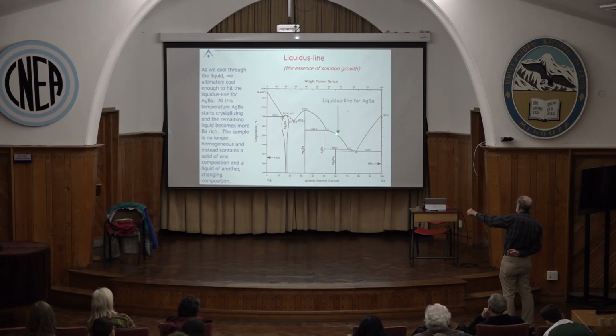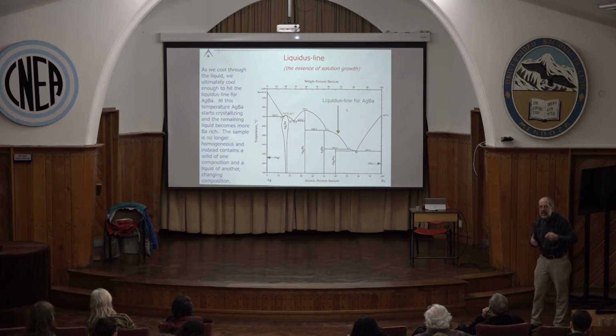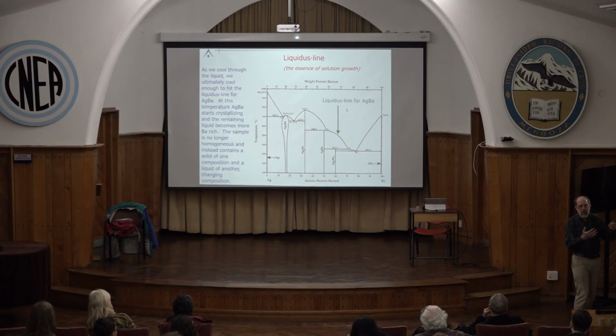But now, when we hit the liquidus line, we start growing crystals of silver barium, and the remaining liquid becomes more barium rich. If we want to grow crystals of silver barium out of the solution, we identify where the liquidus line is, and we hit it upon cooling, we can grow our crystals. That's the essence of how you try to grow a material.